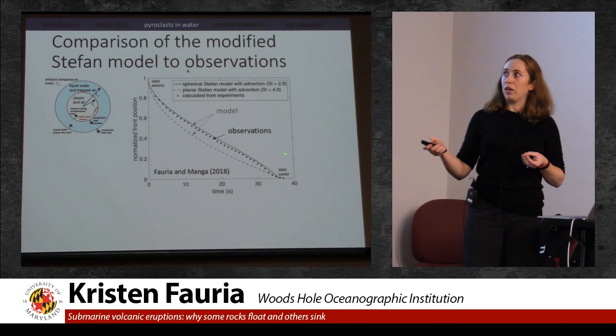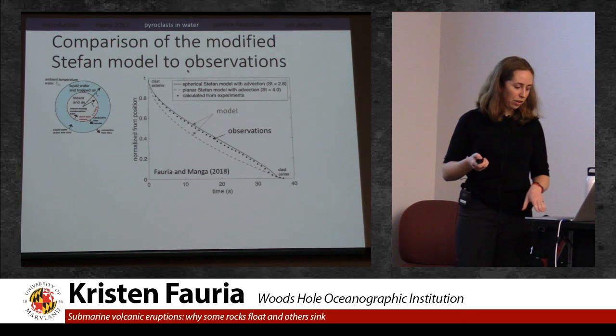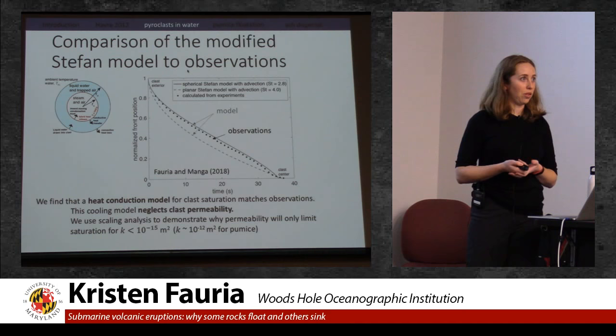And so the black dots are calculated from our observations and the gray lines are modeled via our conduction equation, our Stefan problem. And so we find that we can predict the time at which the condensation interface reaches the center of the clast. And so this lends some support, at least, to our cooling hypothesis, or idea that cooling controls the saturation of porous clasts.